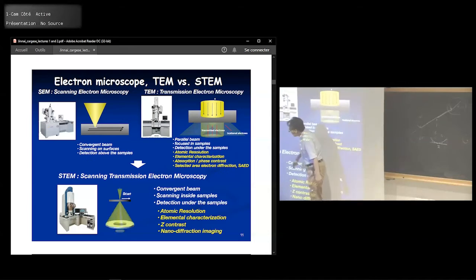There's another one, scanning transmission electron microscope, we call STEM. This is a sort of a combination of these two. So in this case, it's similar to the SEM. We converge the angle, and then we scan the sample. We scan the sample in the sample, okay? So converging beam and scanning inside sample, and detection is underneath, okay, not above, underneath.